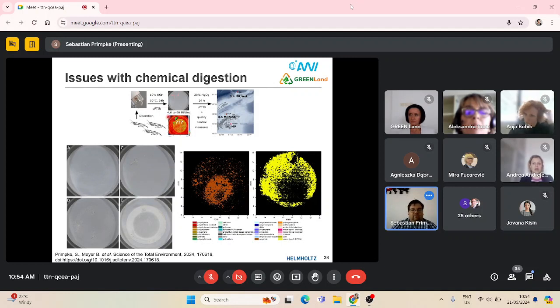5 to 90 microplastics per individual. This is rather high, and it was completely unexpected. But only when I had a look at the filters, you see here barely visible the stomach residues, but sometimes we had this kind of film formation, which was rather obvious. This was a pooled sample of up to 10 stomachs, so that was not analyzable at all,